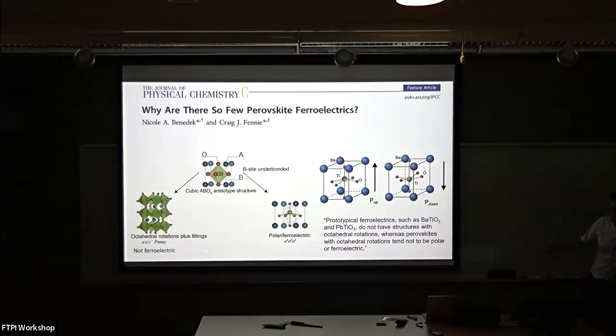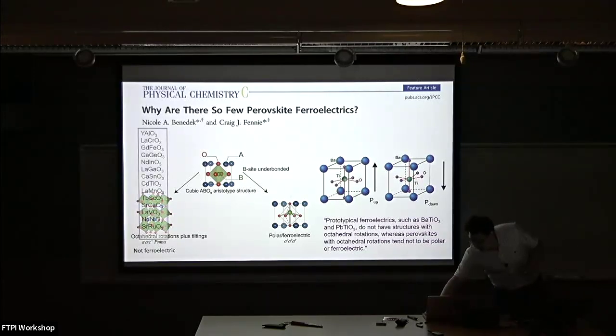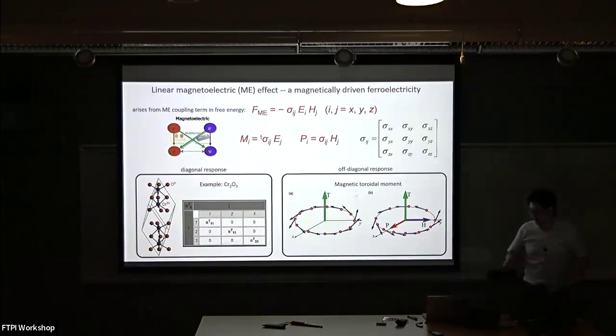All right, so now let's recap our initial research motivation. In this family, they have tons of Pnma orthorhombic perovskite. They are not ferroelectric. In order to make them ferroelectric, one strategy is to change the lattice from cubic perovskite to bilayer perovskite. That is the hybrid improper ferroelectricity I have introduced. But what if we don't change the structure here, and we find some way to induce ferroelectricity in the Pnma perovskite? It sounds impossible because the space group is centrosymmetric, but that's not the case if we use a magnetic degree of freedom. After the magnetic freedom comes in, we can still make the Pnma perovskite ferroelectric.